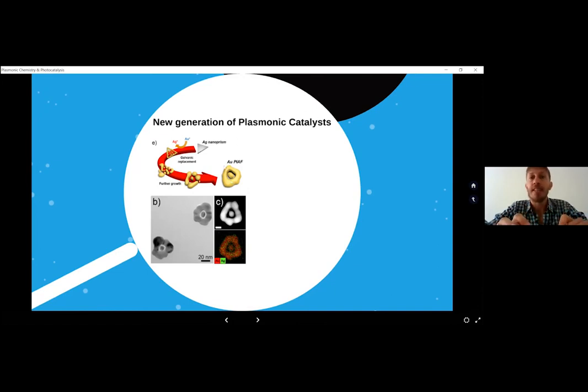So here, we designed these particles, which we call particle in a frame, because we design these structures where you have a central particle, which is surrounded by a frame, in this case made out of gold, and the enhancement in this inner particle is huge. And also the available area for molecules to sit on top of these nanoparticles is huge, right? Which is something that we also need in catalysis. We need a lot of surface area because the reactions happen on the surface of these nanoparticles.